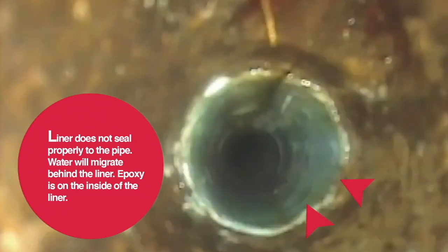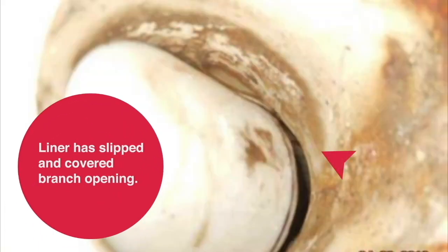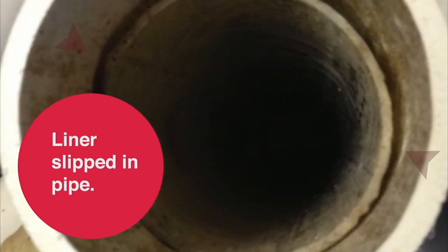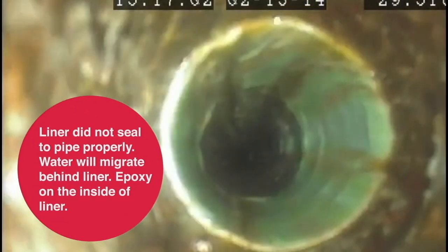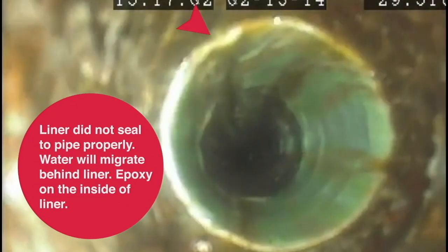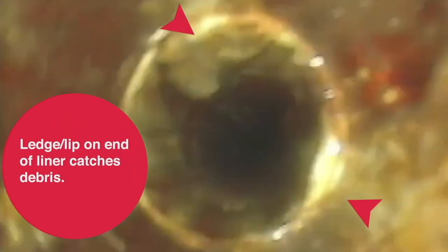To date, multiple lawsuits in the state of Florida point to the future problems facing the installer and the property owner because over time, the liners do react to gravity and slip down to cover branch openings, and the unfinished edges on each end of the gapped liner allow for water to get behind the liner and to deform the shape. These unfinished edges also provide lips and ledges that catch debris. Some installers will tell you that they cut slits in the impervious coating to allow epoxy to bleed out, but this step has little or no effect on the liner's overall ability to adhere to the contaminated pipe surface.